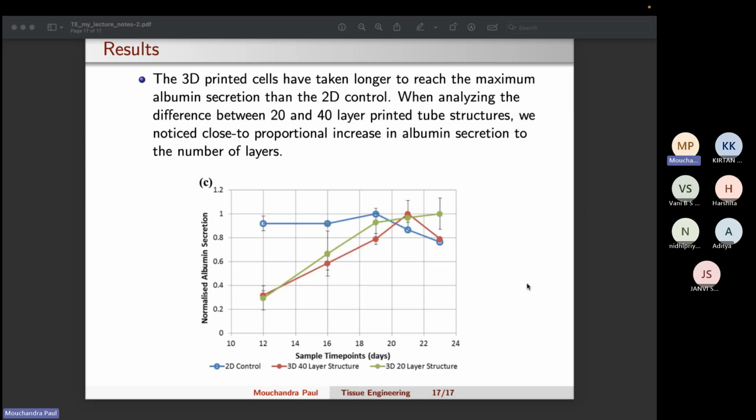So this result also helps you minimize the time it takes to create a mature artificial tissue using stem cells. Rather than starting only from stem cells, 3D printing the stem cells and then doing the differentiation process, which will take much more time, you can harvest the cells which have completed, say, 50% of the differentiation process. You harvest those cells and 3D print them, and then the maturation of the entire tissue will take you less time.